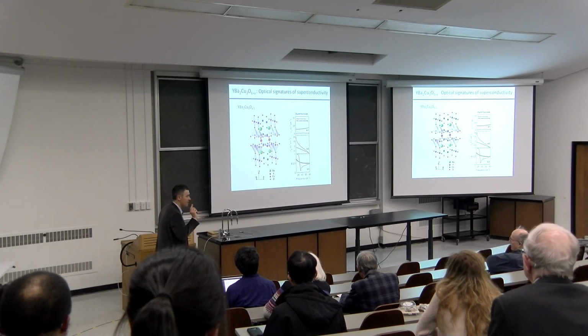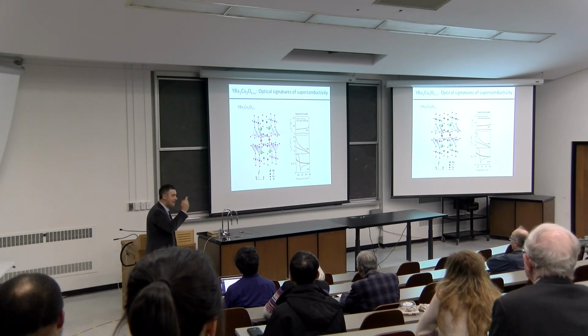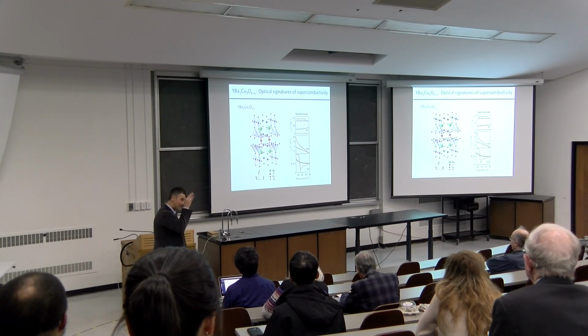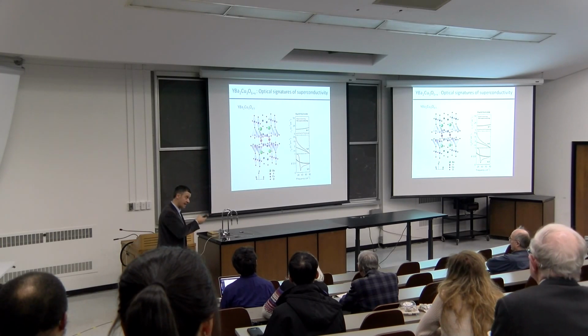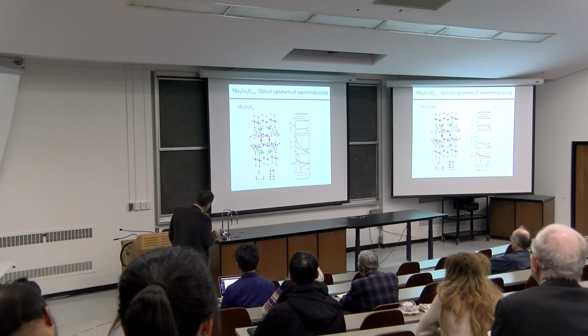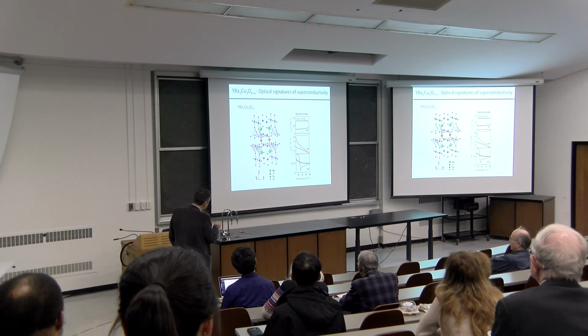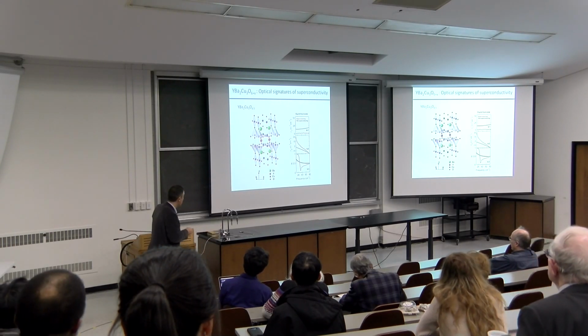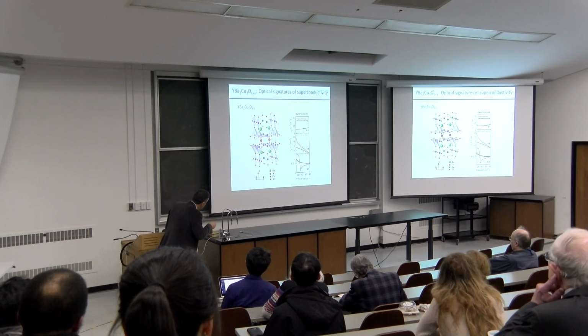Actually, copper is not the right example, but in, say, a metal, you have a plasma edge at a frequency that depends on the square root of the number of free electrons that I have. In this case, I find a plasma edge, which is related to the density of Cooper pairs that are tunneling between these planes. Okay? And this is an extremely sharp edge at very low frequencies.